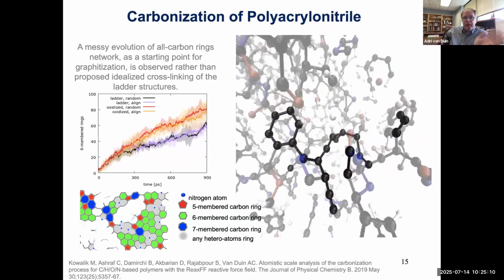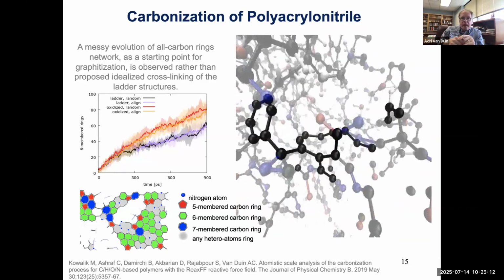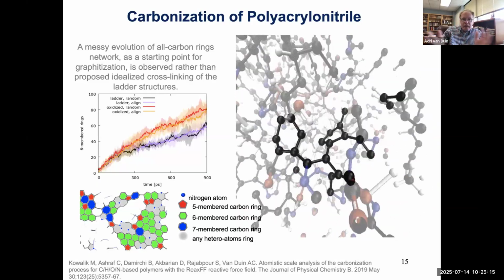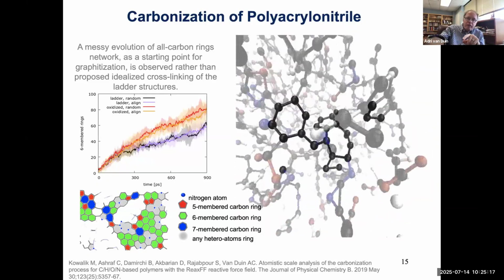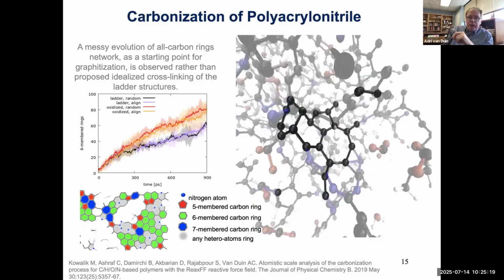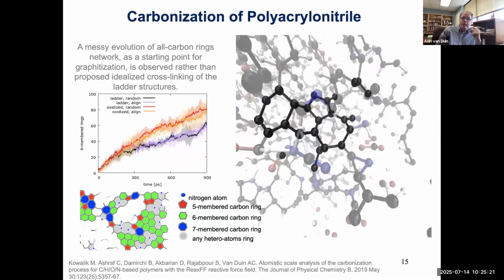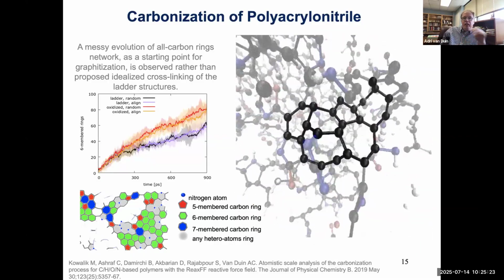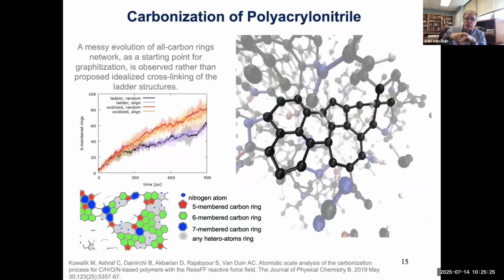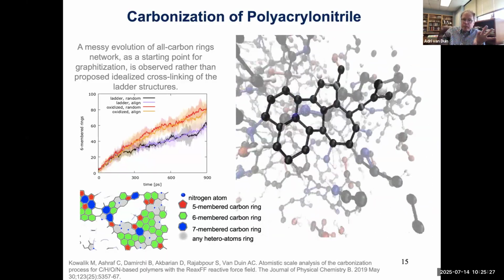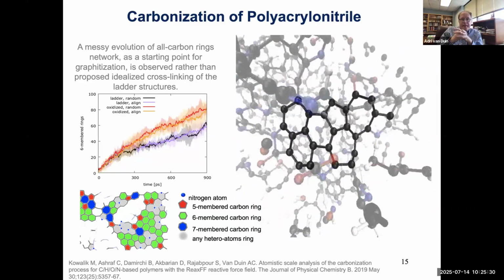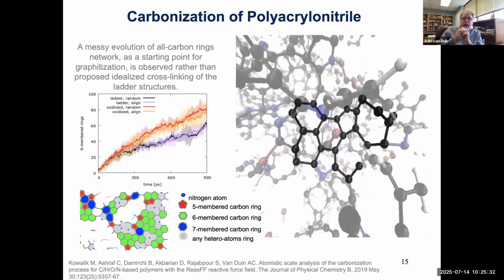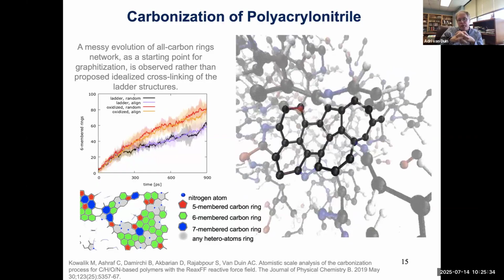this is not a clean process. There's a forward pattern. You see that there's clearly the molecular mass is growing. We see some early 5-membered rings growing. The 5-membered rings are typically kinetically more stable, but eventually, when we get better conductivity, they turn into 6-membered rings. But it's not a straightforward process. By no means is it a very clean, defined process. There are all sorts of stochastic processes going on.